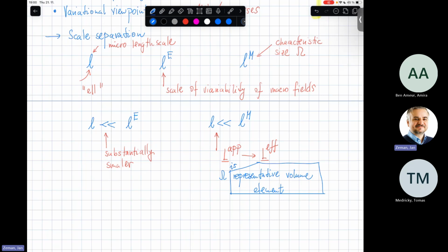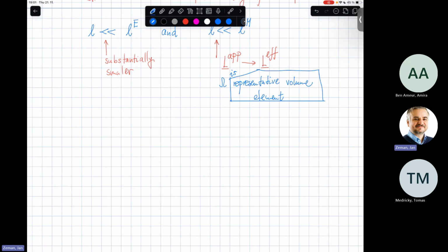And these conditions must be satisfied simultaneously. So, in that logical sense, both must hold. So again, I need to have a sample of my microstructure which is substantially large to get rid of the effect of the boundary conditions. And I also need to solve a micro problem in which this doesn't hold, right? So two things, two examples, again, just to finally conclude, where these are violated.